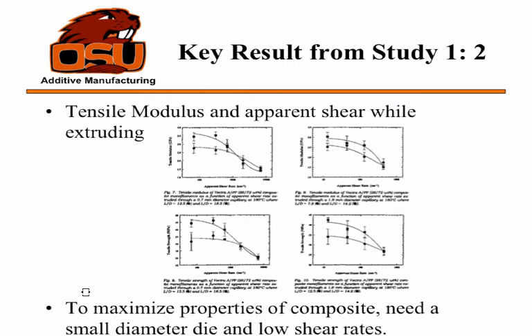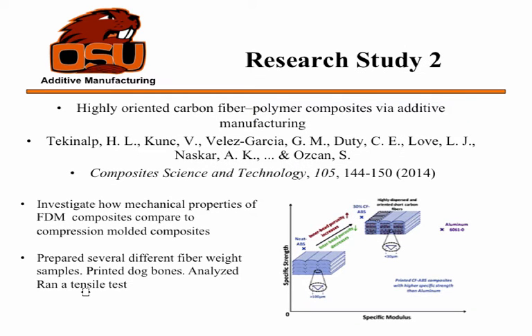And the second part was more of an actual processing thing. They were looking at the apparent shear rates that they were extruding through these dies. These charts are a little small, but on the x-axis you have the apparent shear rate, and the y-axis should be your modulus. And those are just different die diameters. The big thing to take away is that as you increase the shear rate, you end up decreasing the modulus. The ones on the left and the ones on the right are different die diameters. So if you want to make one of these filaments, you want to use a small die diameter and low shear rates.